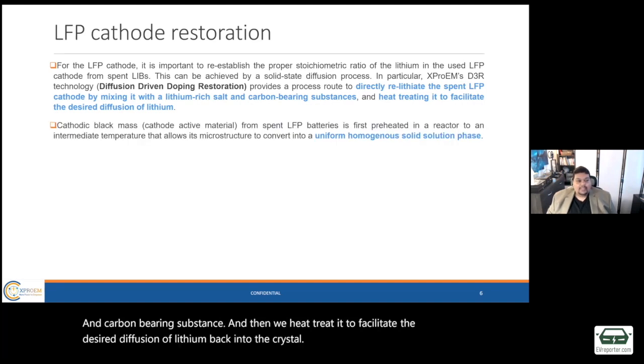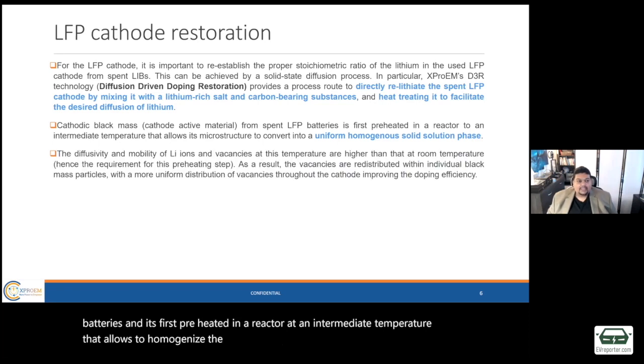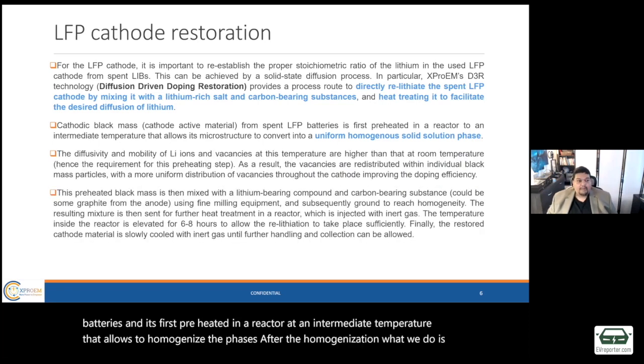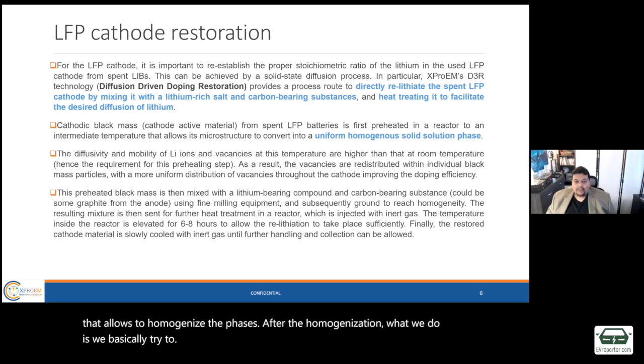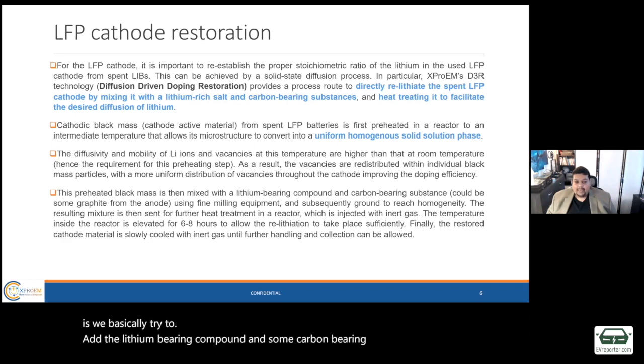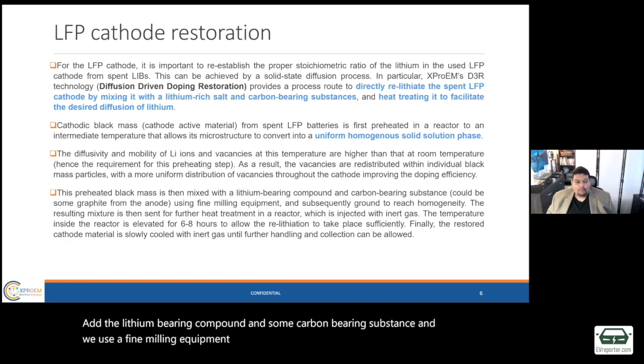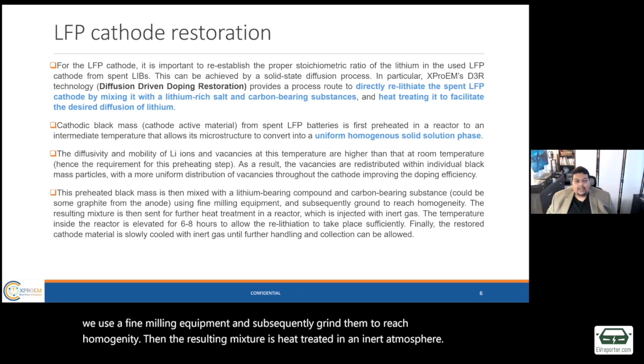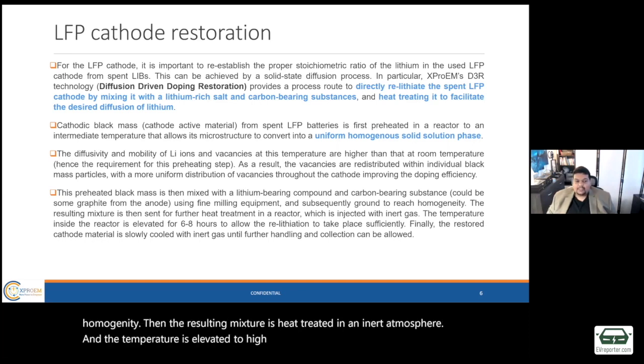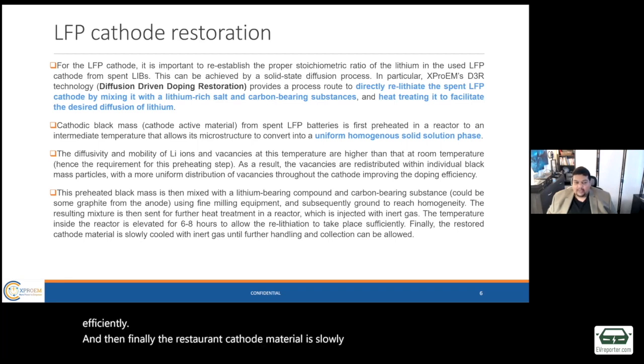So first, we take the cathodic black mass from spent LFP batteries, and it's preheated in a reactor at an intermediate temperature that allows the phases to homogenize. After the homogenization, we add the lithium bearing compound and some carbon bearing substance, and we use fine milling equipment to grind them to reach homogeneity. Then the resulting mixture is heat treated in an inert atmosphere, and the temperature is elevated to high temperature. The residence time is around 6 to 8 hours. Then the relithiation can take place efficiently. And finally, the restored cathode material is slowly cooled under inert gas conditions, and the collection is allowed.